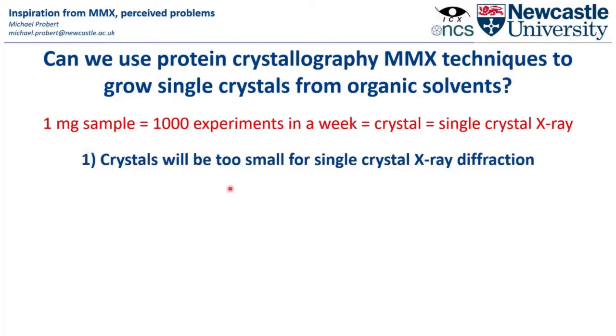One worry we started off with, which turned out to be a little bit unnecessary, was the size of the samples being formed. If you actually do a back of the envelope calculation, we're still far in excess of the amount of material in each crystallization condition for analysis, so that's okay, we don't have an issue. If we did, we could always turn to micro-ED as a solution if we can form our crystals.